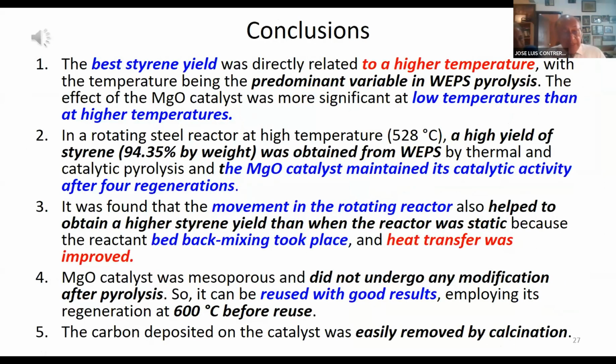Well, these are the conclusions. The best styrene yield was directly related to a higher temperature. The effect of the magnesium oxide catalyst was more significant at low temperatures than at higher temperatures. In a rotating steel reactor at high temperature, a high yield of styrene was obtained from waste by thermal catalytic pyrolysis, and the magnesium oxide catalyst maintained its catalytic activity after 4 regenerations.